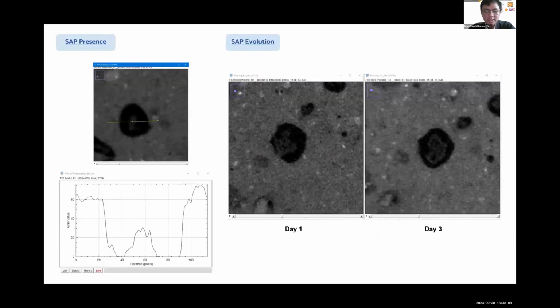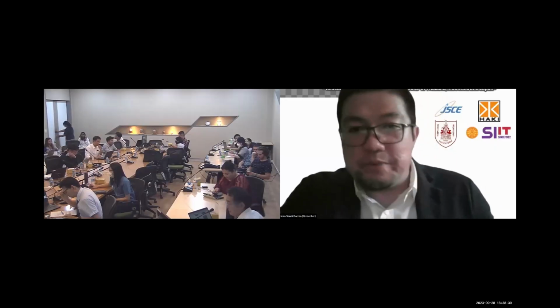To prove the presence of SAP, we can scan a specimen with SAP that absorbed some tracer. So SAP will be able to be identified. From the line profile, SAP is shown in the center of the pore. SAP evolution can also be observed. The SAP will be smaller because of the release process. For summary, we can say superabsorbent polymer is effective as an internal curing medium based on compressive strength and pore properties. Thank you. Okay, that's our presentation.